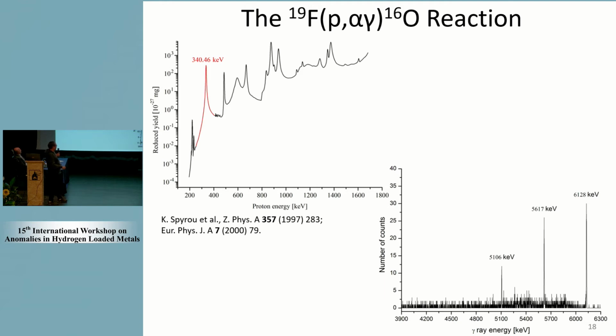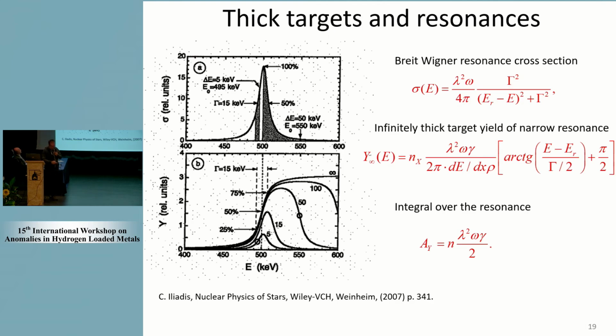This is when you lose a gamma from annihilation, so we call it a single escape, and then you lose both gammas from annihilation of the positron, so this is a double escape. So when you study a resonance, the best is to have a thick target, and then you get such a step function, and this is the function that you use to fit this step function, and this is the resonance strength. This is then directly related to the cross-section. So by determining the resonance strength, you can, from the cross-section, determine the electron screening.